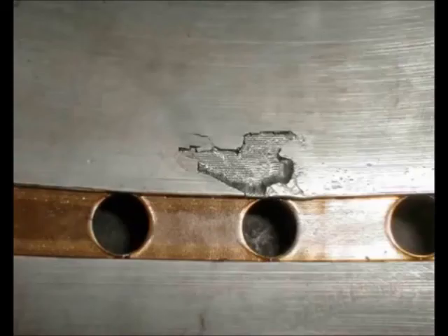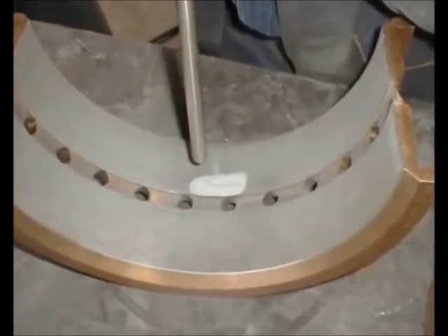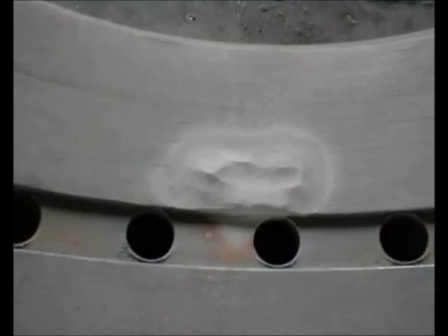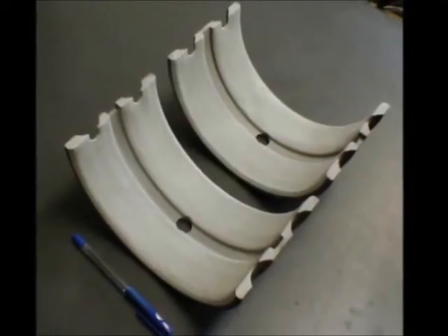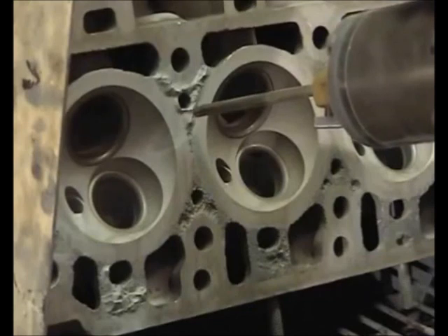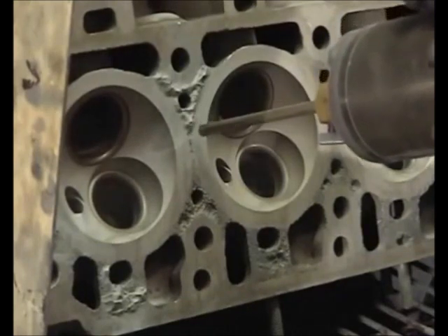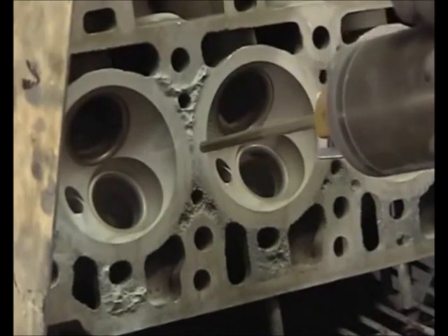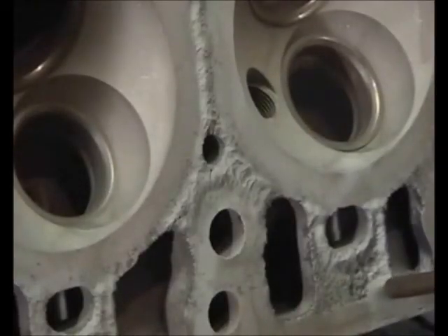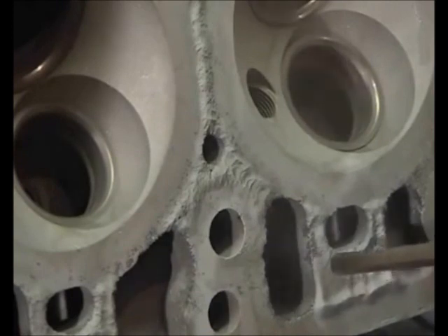Cold spray. In cold spraying, particles are accelerated to very high speeds by the carrier gas forced through a converging, diverging, DeLaval-type nozzle. Upon impact, solid particles with sufficient kinetic energy deform plastically and bond mechanically to the substrate to form a coating. The critical velocity needed to form bonding depends on the material's properties, powder size, and temperature.